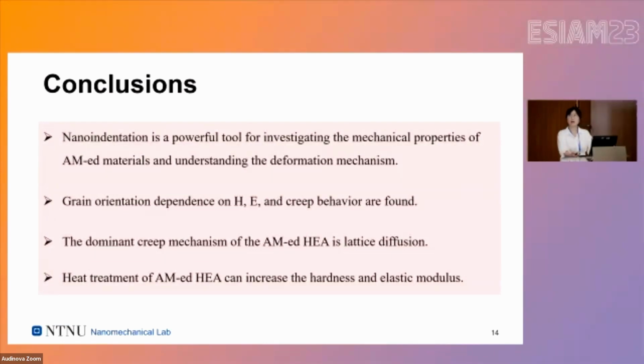So my conclusion is that nanoindentation is quite a powerful tool for investigating the mechanical properties in AM and understanding the deformation mechanisms. In our current work, we found the grain orientation dependence on hardness, elastic modulus, and creep behavior, and the dominant creep mechanism of the additive manufactured high entropy alloy is lattice diffusion. We also found that the heat treatment can increase the hardness and elastic modulus.